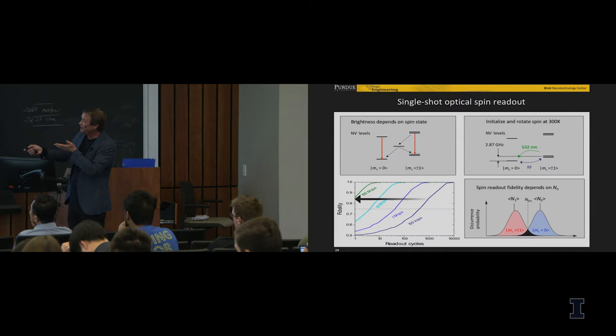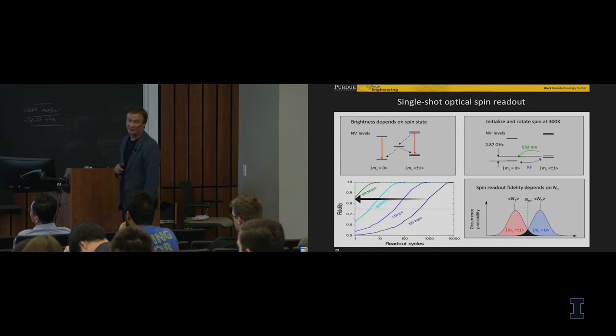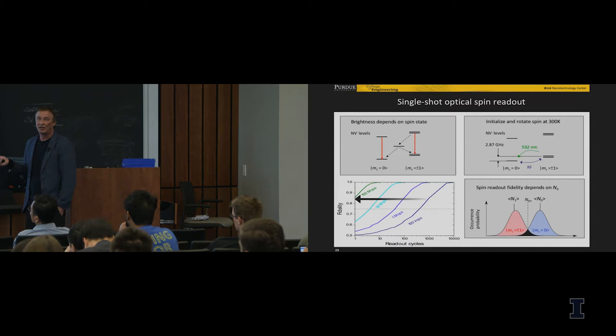So if you pump too long, everything would go eventually here. So you have to detect your spin state within a time shorter than the lifetime of this metastable state, which is 300 nanoseconds. But within 300 nanoseconds, conventionally, you have only about 100,000 counts per second. So if you recalculate it for 300 nanoseconds, you have far less than one photon. So you cannot detect it. You just have way too few photons.